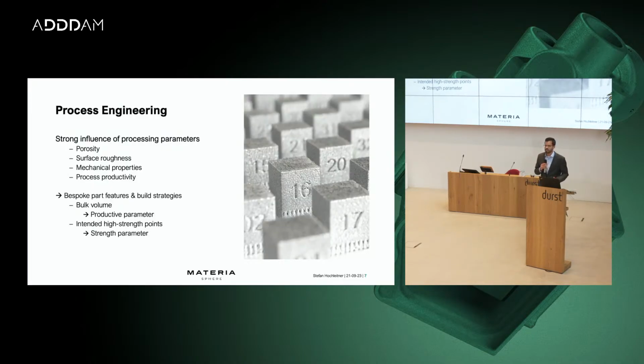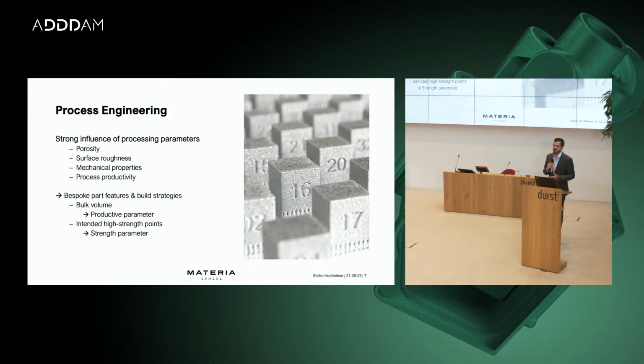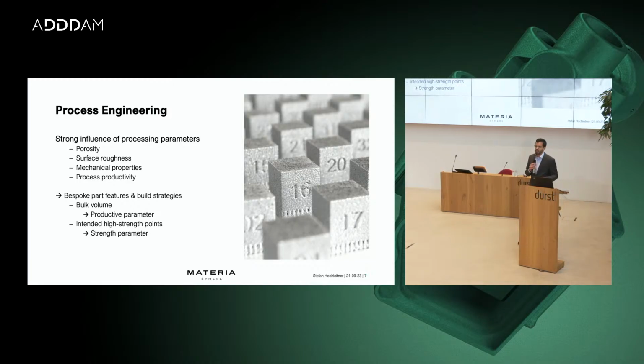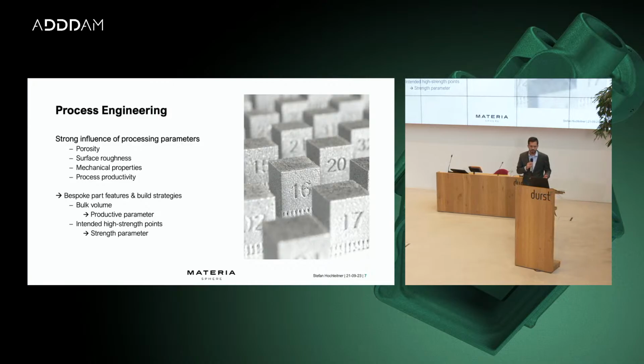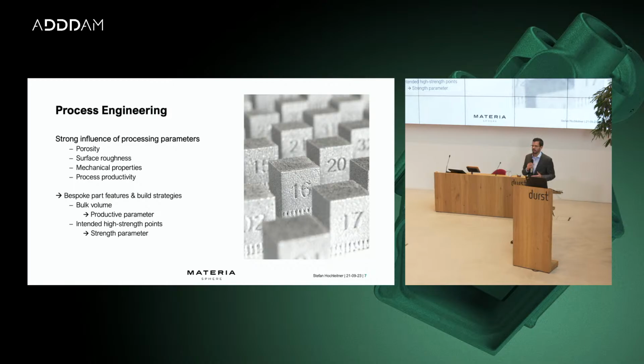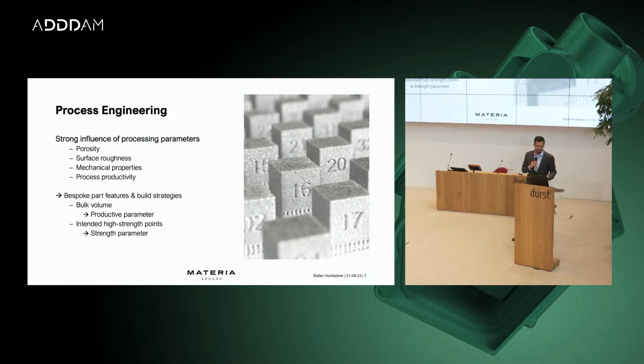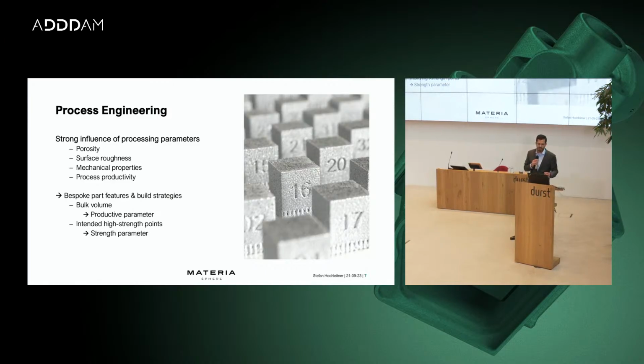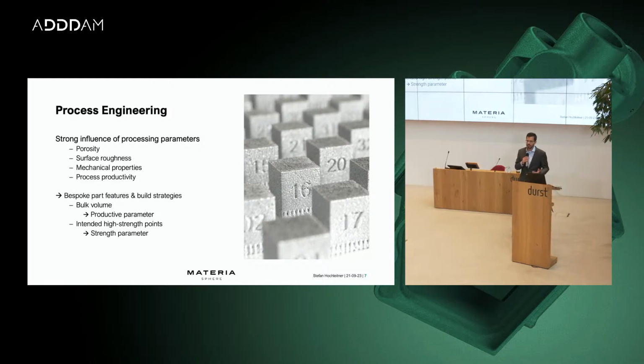As I mentioned before, the process is as essential as the material itself, because you got a very strong influence on the part quality with the processing parameters. Depending on laser speed, laser power, and the hatch spacing, for some examples, you can influence the porosity, surface roughness, mechanical properties, and also the process productivity itself. So it's possible in the future to build bespoke part features and build strategies depending on how your part should perform. You could print your bulk volume of the part with a completely different parameter set that has a focus on productivity, and you can print high-strength points in the material with, let's say, a strength parameter, which is slower but enables a greater strain resistance of the parts.